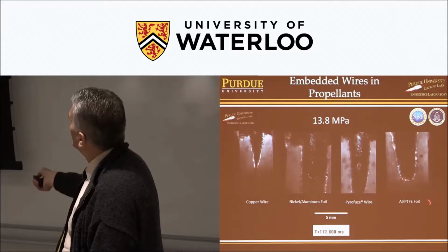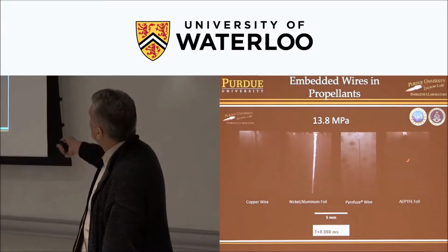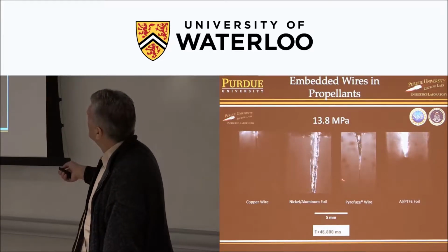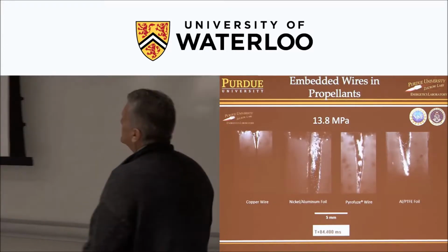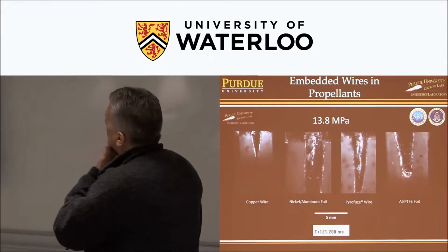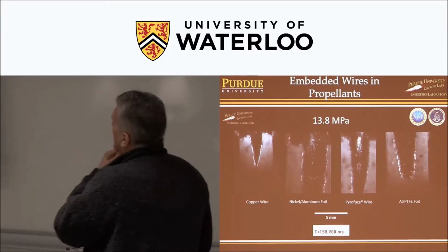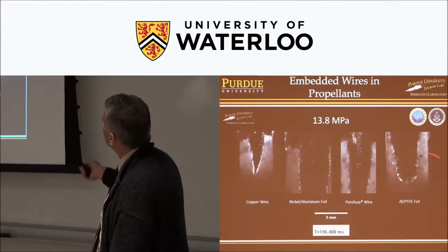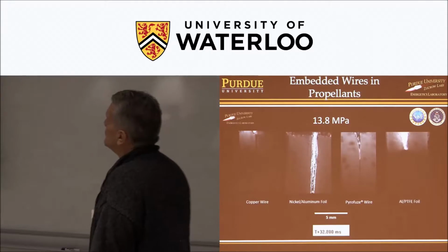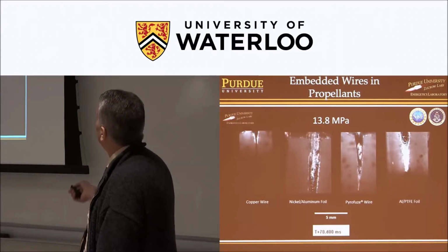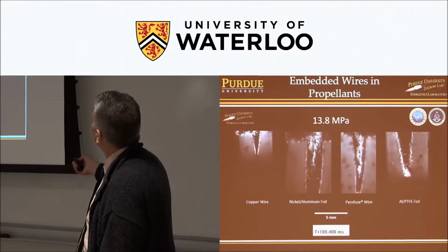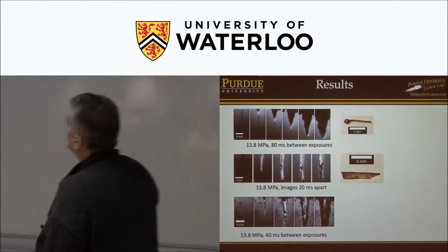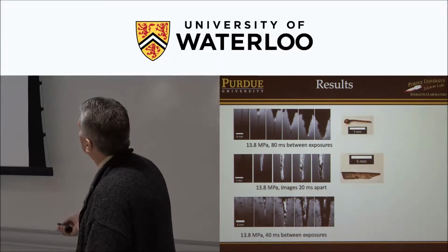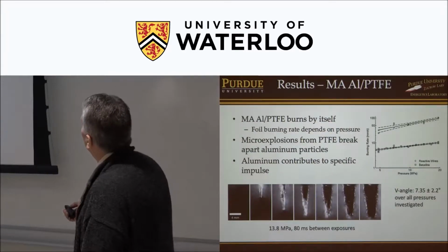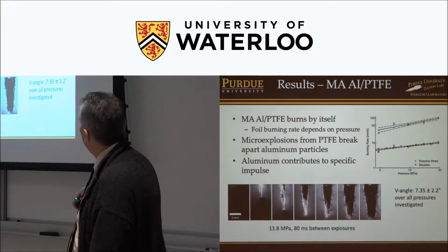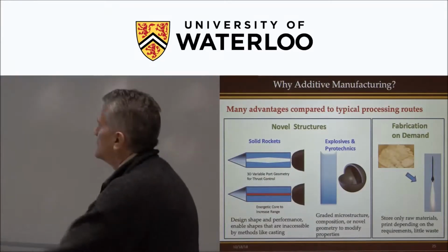Pyrofuse is a little bit slower, and our aluminum Teflon foiled material is pretty fast, but maybe a little bit slower than the Pyrofuse. The disadvantage of these materials is that in all their cases, the products are basically non-reactive and form big clunky particles that go out through your nozzle. In this case, the particles disperse into aluminum, and as I mentioned before, propellants often use aluminum anyway, so it'll form small droplets and small particles. So this shows you some of the products that come off from these types of experiments. And this is the aluminum Teflon type of material that forms a small dispersive type of thing.